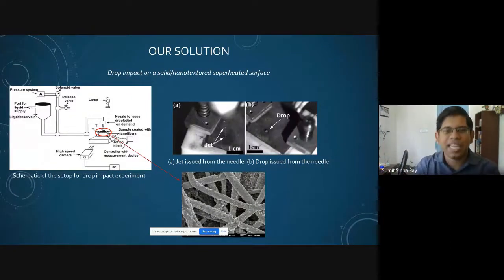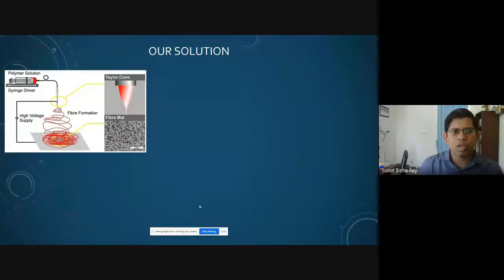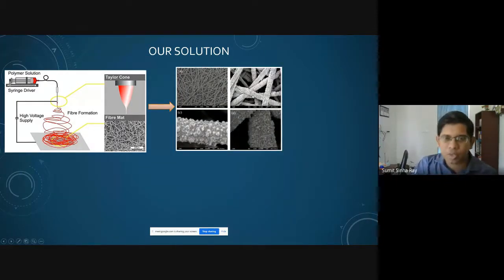The question is how to easily manufacture this. One of the easier solutions is electrospinning. If you are interested, I can explain the phenomenon of electrospinning in detail. However, the basic detail here is that a polymer solution is being pumped through a needle, and this needle and a collector are electrically connected to a very high voltage supply of about 10 kilovolts. When the polymer solution comes out from the needle, it gets attracted, overcomes its surface tension, and gets pulled out as a viscoelastic jet. That jet over time solidifies and goes through several bending instabilities, and it gets collected as fibers. These dry polymer fibers are then metal plated, using age-old simple electroplating techniques.